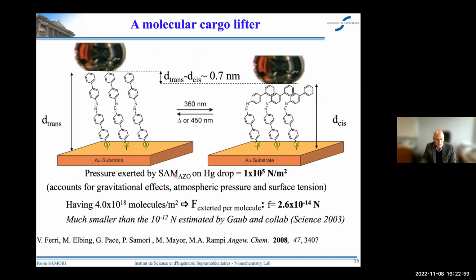And actually, without going into the details, what we found out is that the self-assembled monolayer behaves like a cargo lifter. It can exert a pressure on the mercury drop to lift it up when it is triggering the isomerization from the cis to the trans. The force exerted by a single molecule is very tiny, in the order of 10 to the power minus 14 newton. But actually, we have an Avogadro number of molecules switching simultaneously. And therefore, we can exert an overall pressure of the self-assembled monolayer on the gold on the mercury drop of 10 to the power 5 newton per square meter, which is pretty high in magnitude.